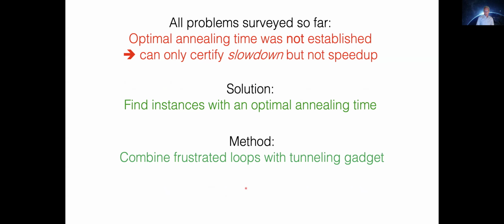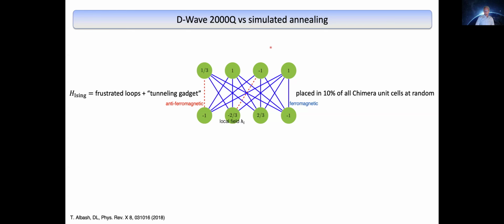All right, so for the problems that I talked about so far, we were not able to establish an optimal anneal time, and that basically only gave us the ability to certify that there was a slowdown, but not ever to claim that there was a speed up. So we looked hard for problems with an optimal anneal time, and it took a few more years, and then we were able to do this for the first time by combining frustrated loops, like on the previous slides, with the idea of a tunneling gadget, which was introduced by the Google group. So this was the particular gadget that we added to the frustrated loops in this paper, again, with Tameem Albash from 2018.